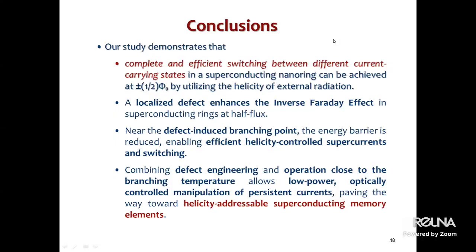That means some connection at some point. The ring is on top of the substrate. Some points of this connection can have a good connection, some a bad connection. That means the sink, or the transfer of heat to the substrate, at some points can be large, at some small. That means some points of the ring will become hot, some points of the ring will become cold. This is the situation which I described. But there is basically a symmetry: either we consider Tc constant and T fluctuating, or we consider T constant and Tc fluctuating.